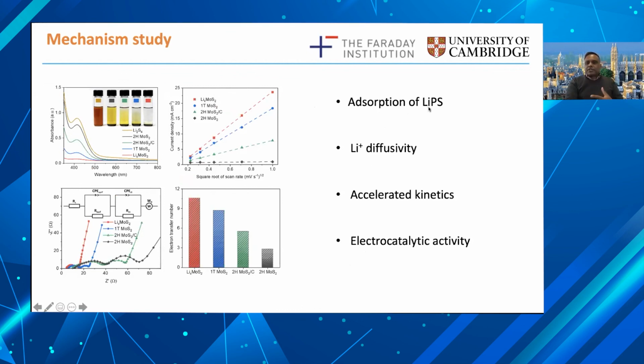has sulfur in it, the interaction of the sulfur with MoS2 is quite strong. So we have a large adsorption of the polysulfides that are formed in the reaction at the cathode, and that's borne out by this adsorption data, where we place the different polysulfides in the solution with our 1T MoS2, and we can see that the 1T phase MoS2 has the lowest absorbance. That is, all of the polysulfides are now adsorbed onto the cathode. We can also show that the 1T phase MoS2 has the lowest internal resistance and a very high catalytic activity for the sulfur reduction reactions with specific polysulfides.